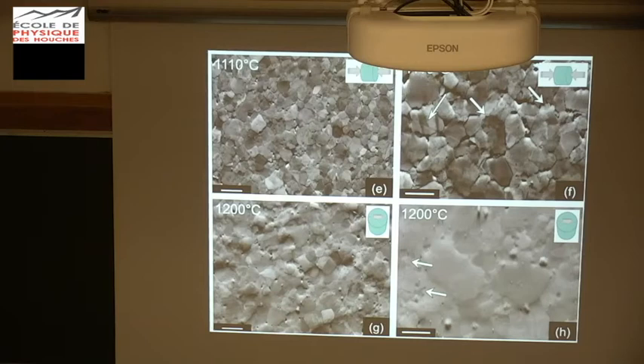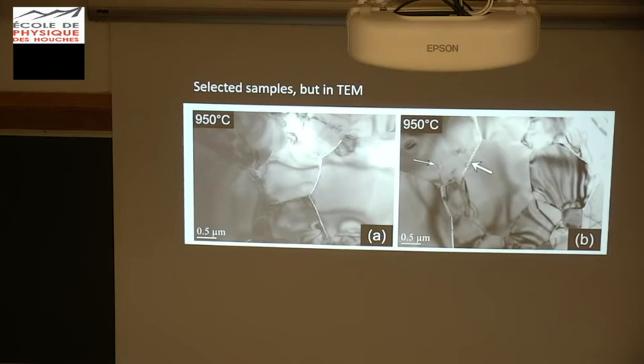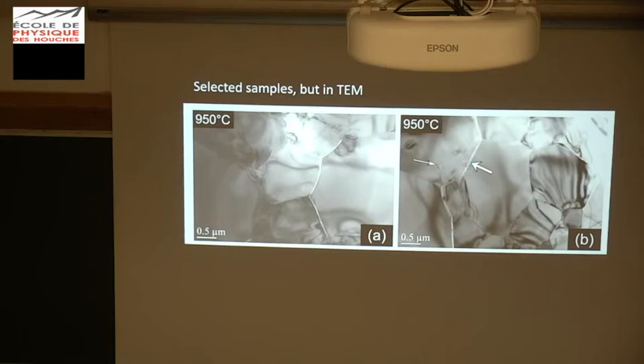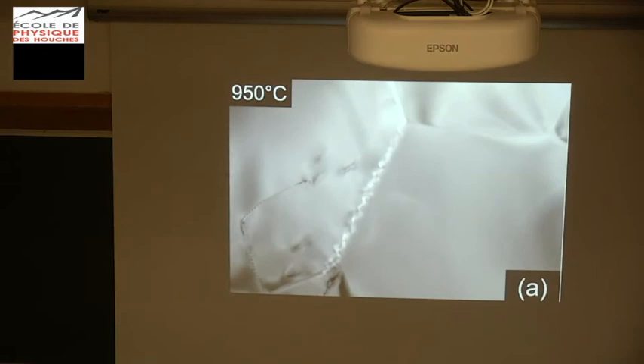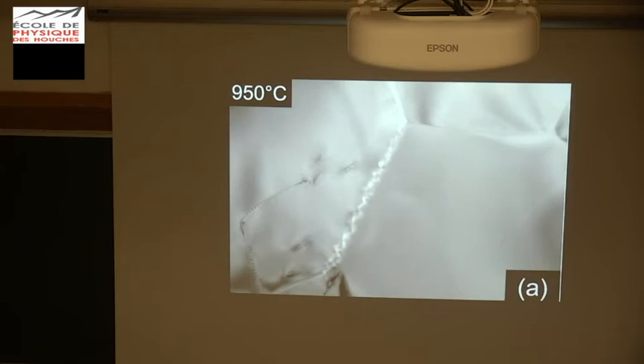Because I'm very picky, and I'm lucky to have good colleagues in France who are really good in TEM, I asked Patrick Cordier to have a look at those weird samples. Going back to the lowest temperature — 950°C — you have nice grains with almost straight grain boundaries, but they are open, they are cracked. Some of them also remain closed. We have this one with a sort of teeth, peaks, asperities, decoration cells — we're still fighting with each other about what to call them. So we zoom into this: closed, tight grain boundaries and open grain boundaries with some steps. If I say steps, you'll start to think it's already disconnections — but maybe not. It's opening in a weird way, and it coexists with dislocations.